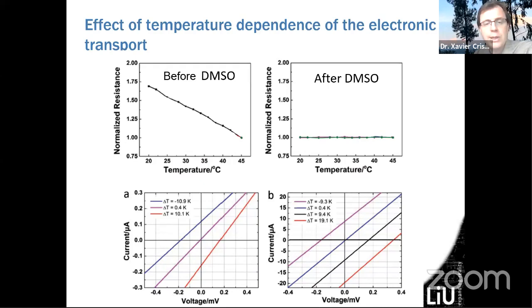The reason is that the resistance is temperature dependent. The resistance of that material changes with temperature, and because of that we have a change of slope of the IV curve when we apply different temperature gradients. That is a little bit annoying, because we would like to have only the slope change due to pressure, but here it's not due to pressure. It's due to the intrinsic transport property of the conducting polymer.